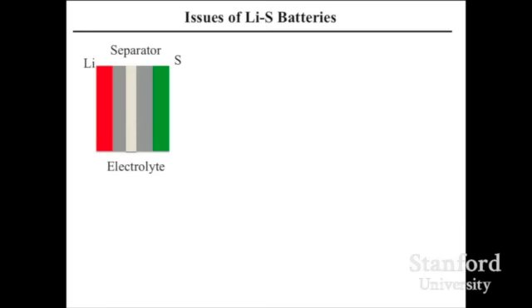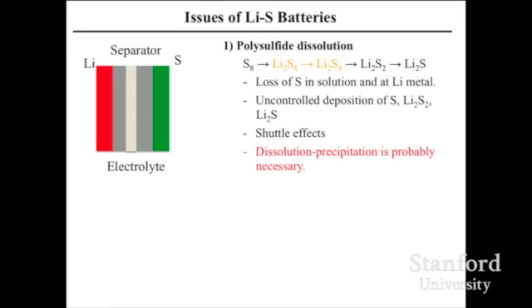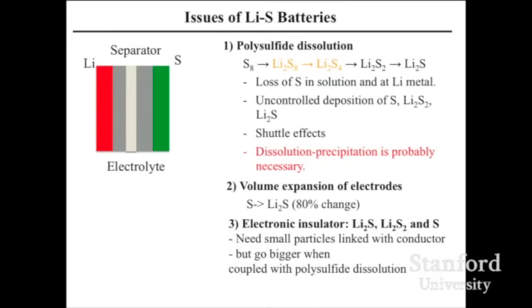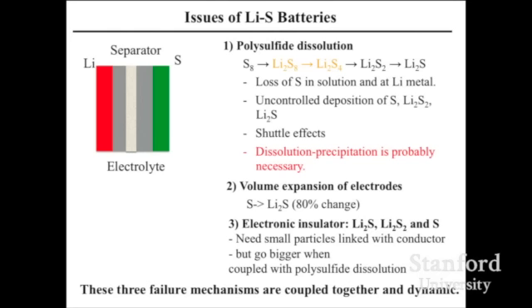What are the problems right here? You have lithium, you have sulfur, and sulfur goes from the S8 molecule, solid, to polysulfide, soluble in your electrolyte. You're losing material, capacity decays very fast. Also volume expansion is big, 80%. And lithium sulfide species are not that conducting electronically. Eventually, these three things couple together and become a nightmare to deal with. It's so hard to make sulfur work.